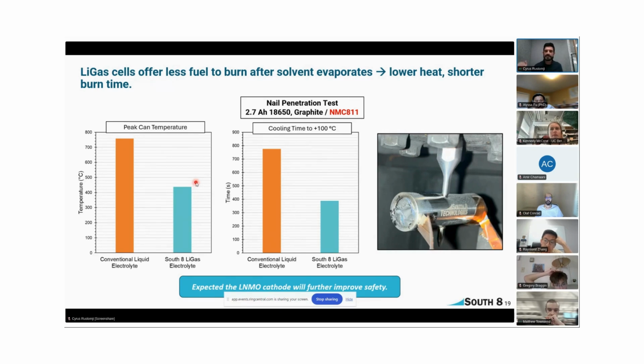And of course, this is a dead short, which didn't give much time for the cell to evaporate all the solvents out of there, so you do see a thermal event, but the total temperature is less. Furthermore, with a thermal camera, we judged when the cooling time reached 100 degrees Celsius. The liquid electrolyte took considerably longer, on the order of 15 minutes, whereas the South 8 liquefied gas cell cooled down much faster, in about half the time. So this really reduces the tendency for thermal propagation from one cell to the next.